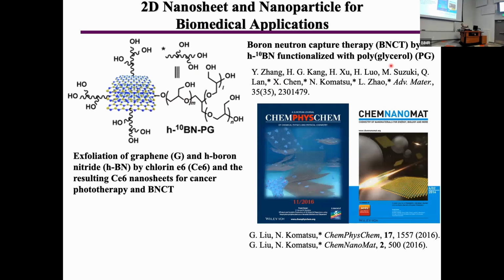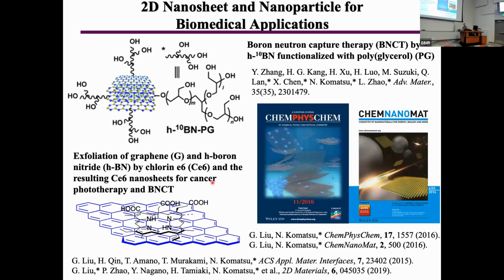This is a very general method to exfoliate 2D materials. One is graphite to graphene, and the others are molybdenum disulfide and tungsten disulfide to nanosheets. We applied this methodology using chlorin e6 as the exfoliant. Chlorin e6 is a very good photosensitizer molecule for phototherapy, for combating cancer. We combined this phototherapeutic sensitizer, chlorin e6, with boron nitride nanosheets for BNCT. It's a bimodal therapy with phototherapy and neutron therapy.